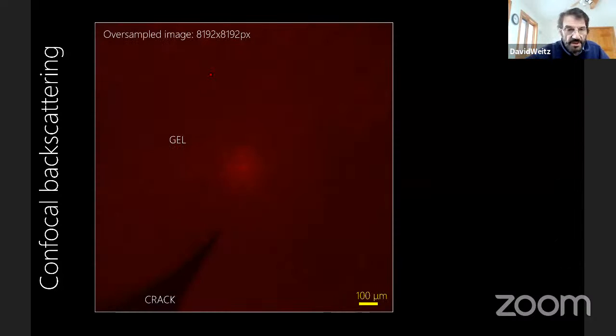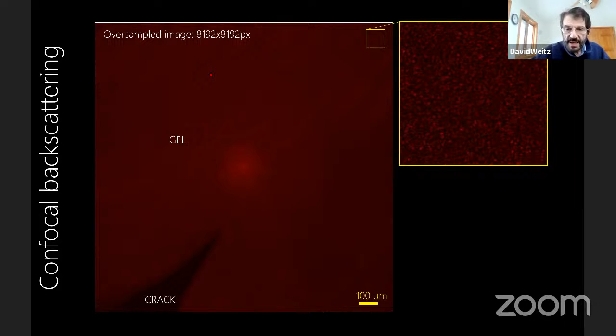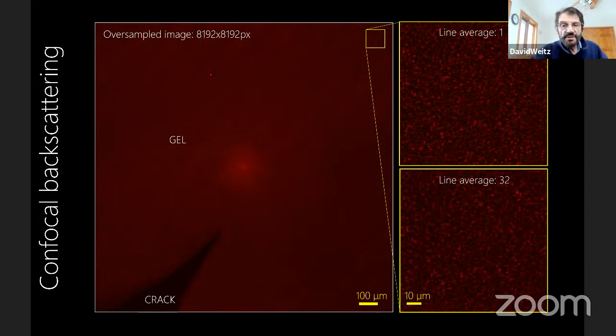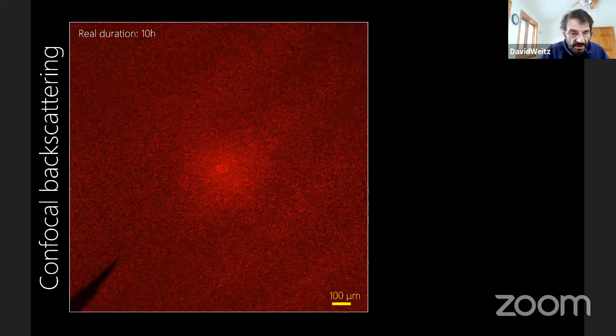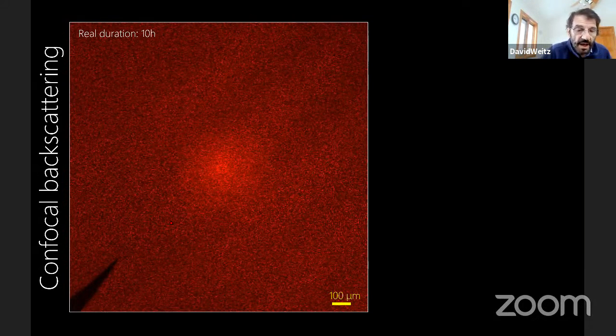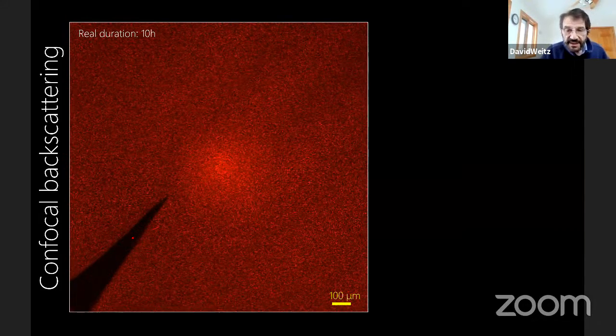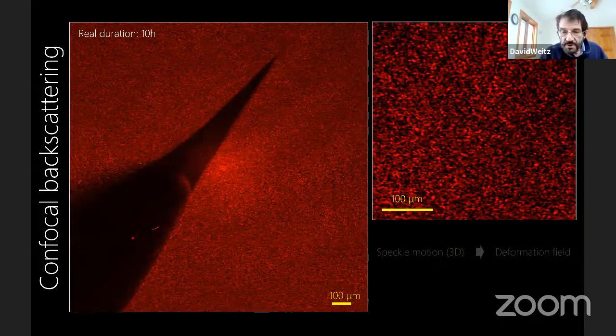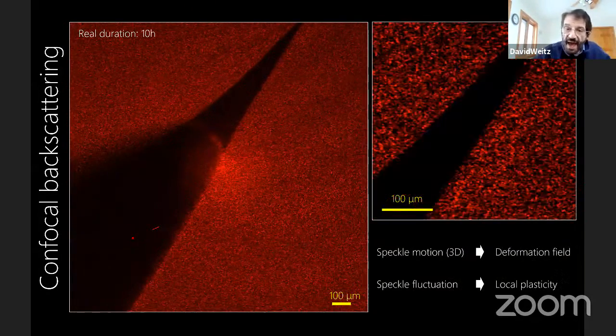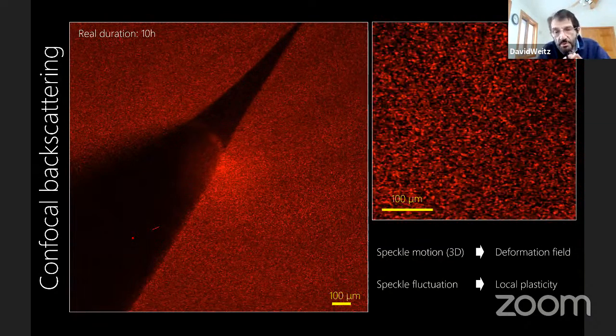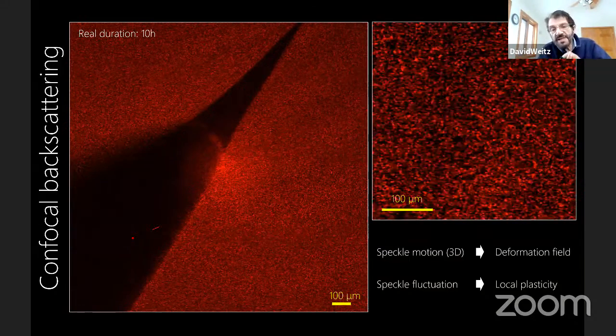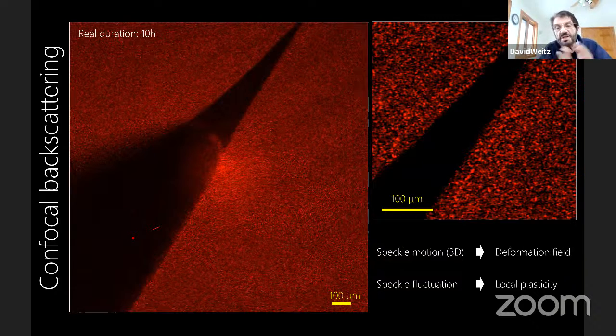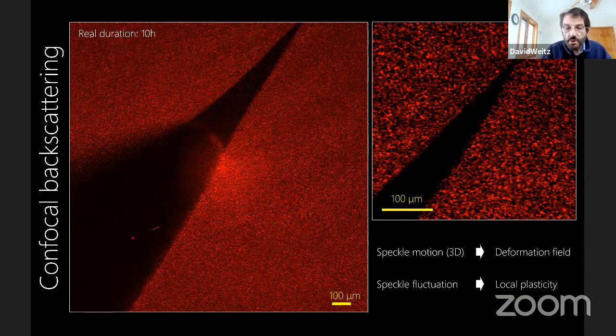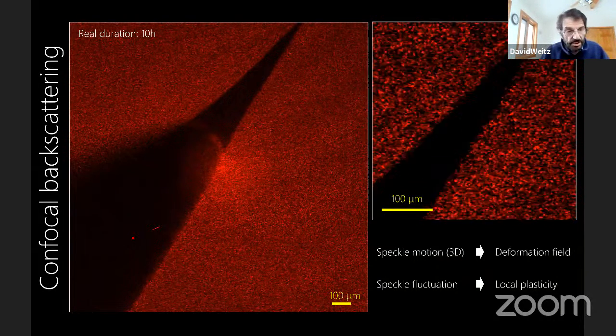So here's an image, and you can see both the image and the speckles in the image. And what he'll do is image both the image itself and the speckles and learn something from that. Let me show you an example. Here's the image, and you can see the crack propagating through the gel, but you can see there are speckles there. And if you blow them up and look at the speckles themselves, you can see the deformation field, you can see the motion. And what I'll show you is you can image the speckles themselves to understand something about the larger scale motion, and you can image the time dependence of the speckles to understand something about the shorter, smaller scale, faster motion. Let me show you what I mean.